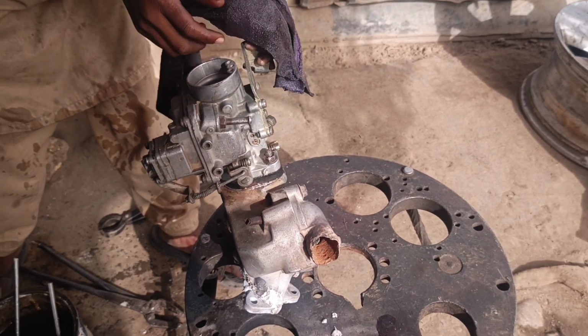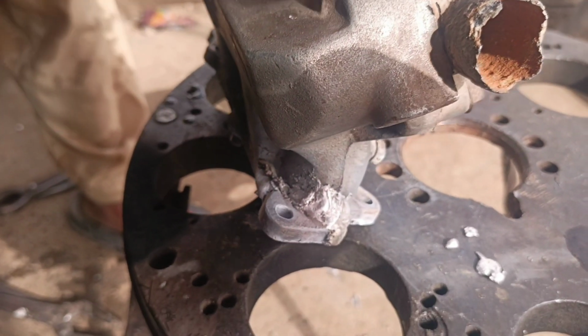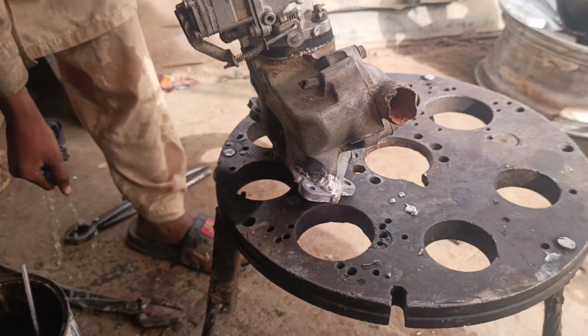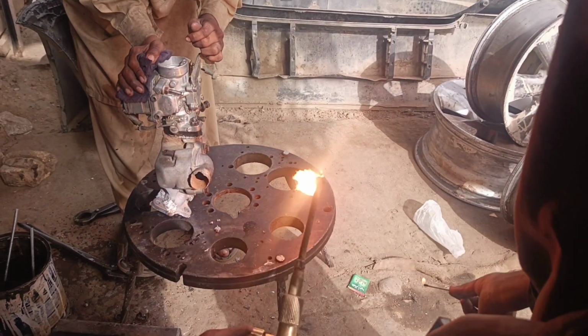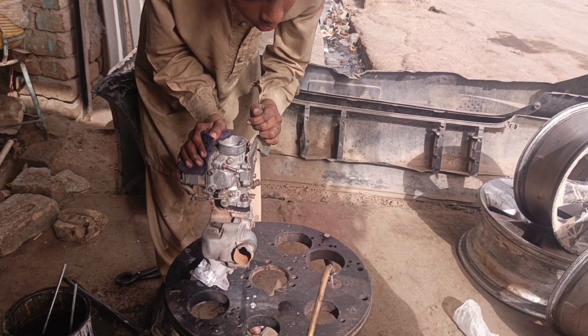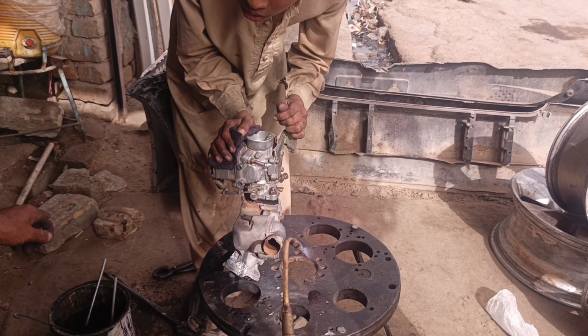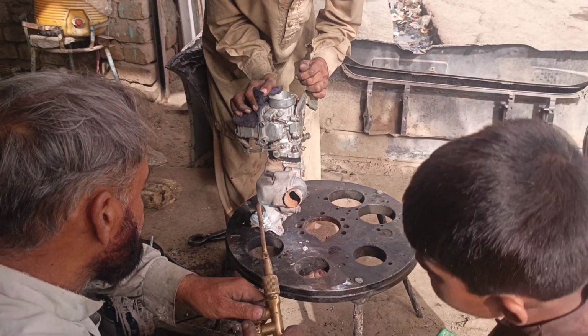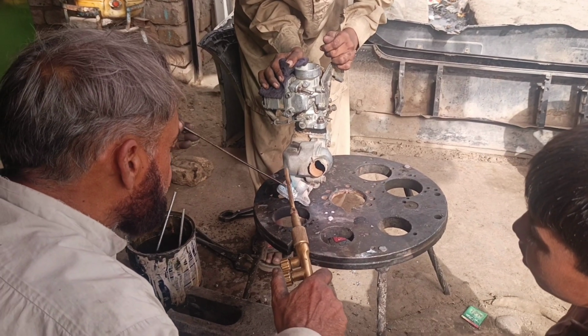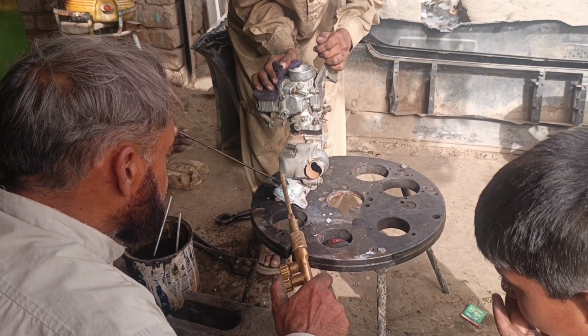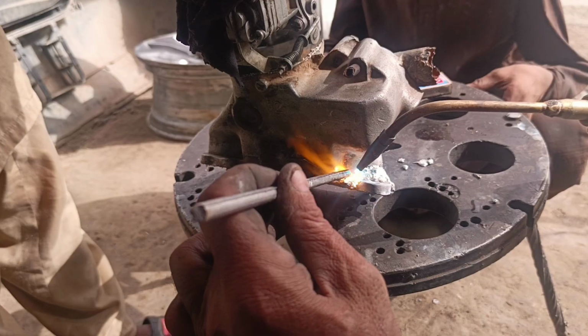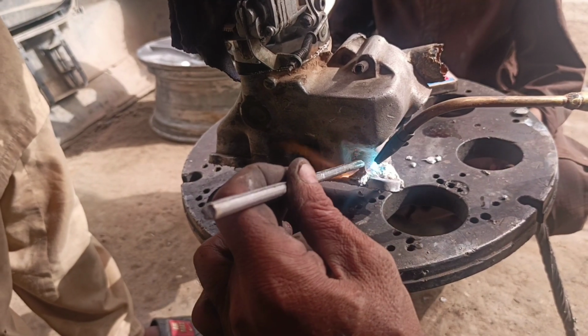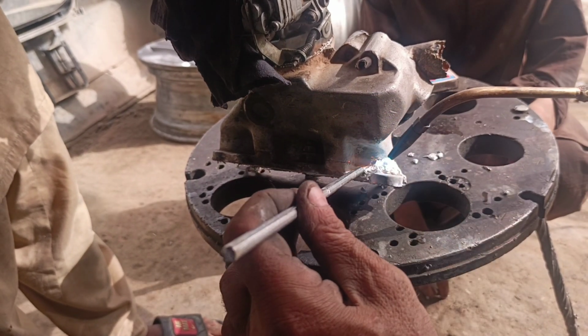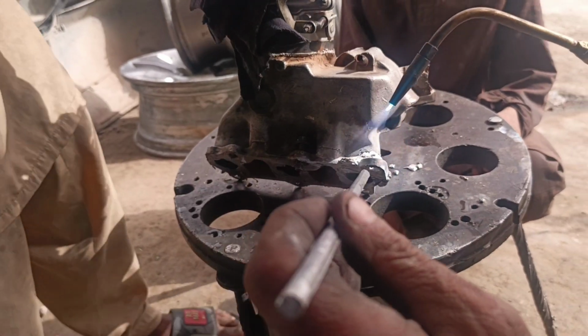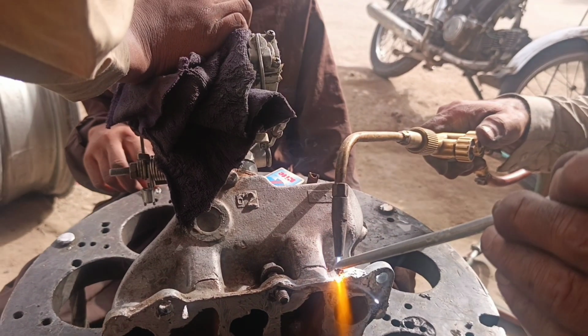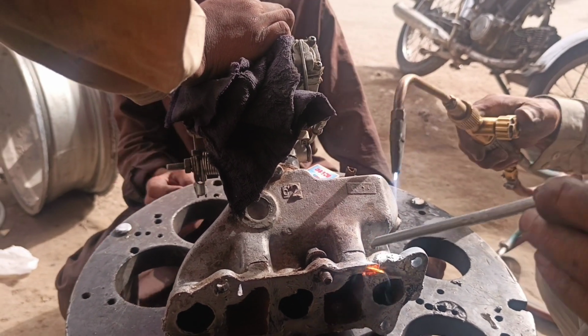Extra filler metal is added to rebuild the damaged mounting flange so it can later be ground back to its original shape. Throughout the process, heat is carefully controlled to avoid distortion, warping, or damage to nearby fuel passages and threaded holes. After the welding is complete, the carburetor is left to cool naturally, allowing the aluminum to relieve internal stresses and produce a stronger, more durable repair. The finished weld is then inspected for full penetration, smooth appearance, and the absence of cracks or porosity, creating a solid foundation for the grinding, machining, and final restoration stages.